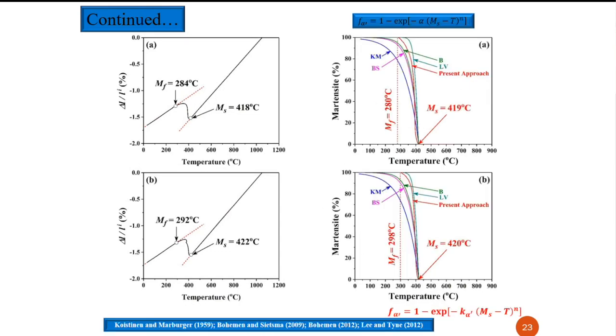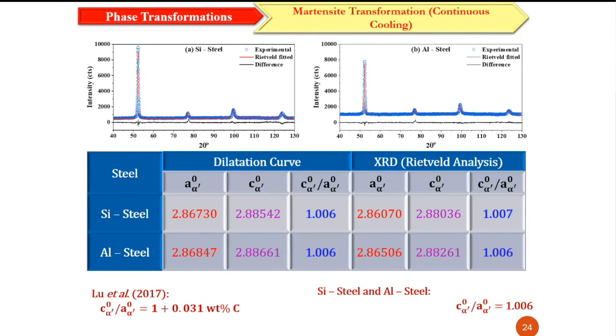We used this to calculate the volume fraction of martensite at any temperature between MS and the MF temperature. We also analyzed the effect of different alloying elements on lattice parameter and how they fit the standard Koistinen-Marburger type equations available in literature, finding that none of them represent the kinetics of martensite transformation very well. We then calculated the C/A ratio of martensite from dilatometry analysis and compared those values with estimates from X-ray, showing a good match fitting one of the equations available in literature.